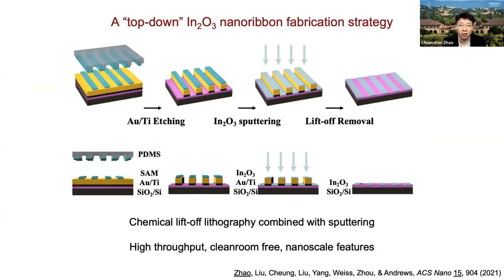So to fabricate the nanoscale semiconductor arrays, we came up with a different fabrication process that combines with sputtering. We use the CLL to pattern the gold nanoribbons first, which is the same process I described previously. Then we sputter the indium oxide on top, and then we can remove the gold as a template or as a metal mask, to have those patterned indium oxide nanoribbons. This process is not limited to indium oxide, but it can also be used for other materials fabrication as well.